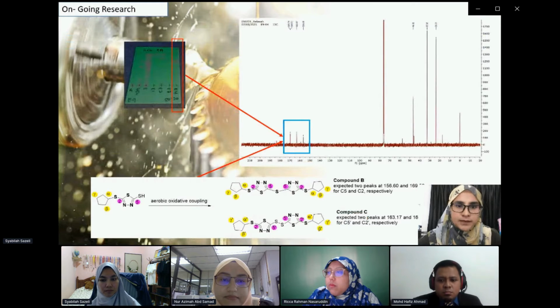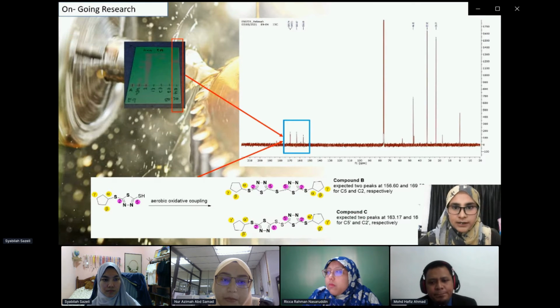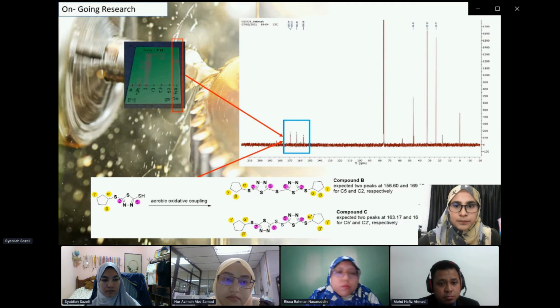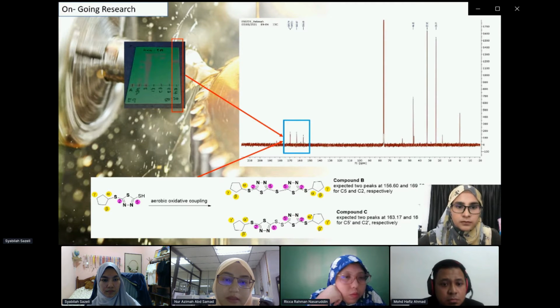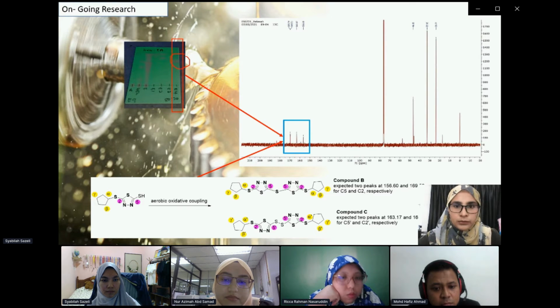So this is the TLC for the sample after being purified for entry 9. It only shows 1 spot. That means 1 compound is available. However, when we sent the sample for NMR, it shows 3 peaks of carbon.